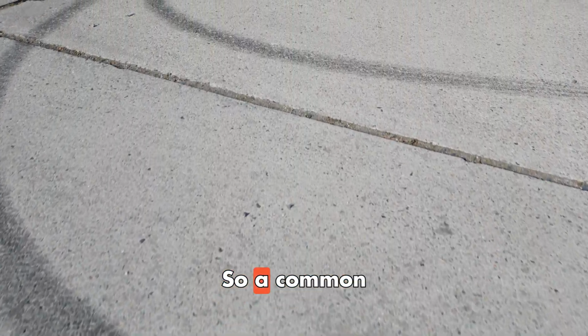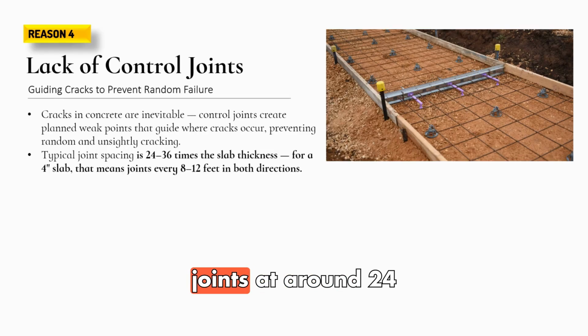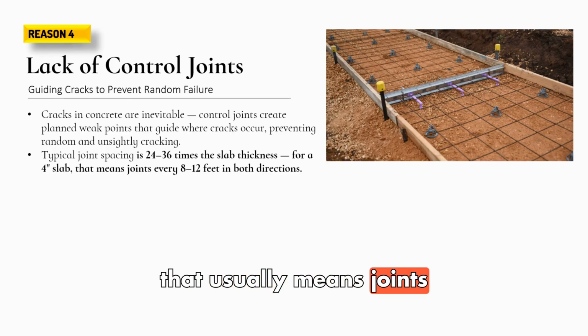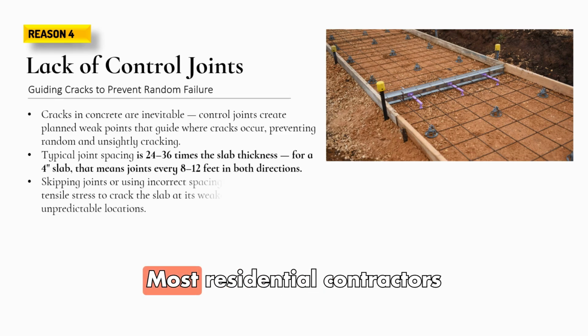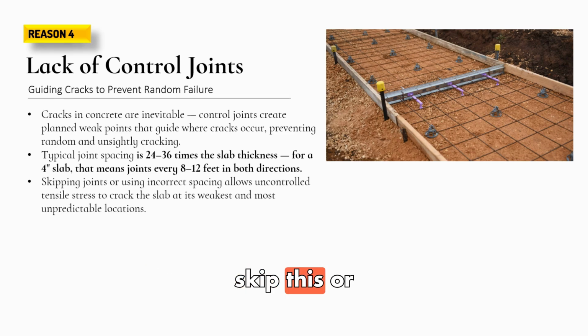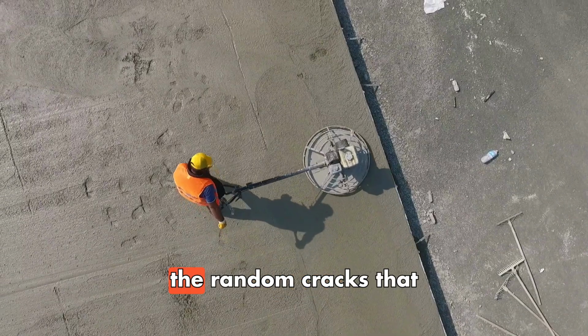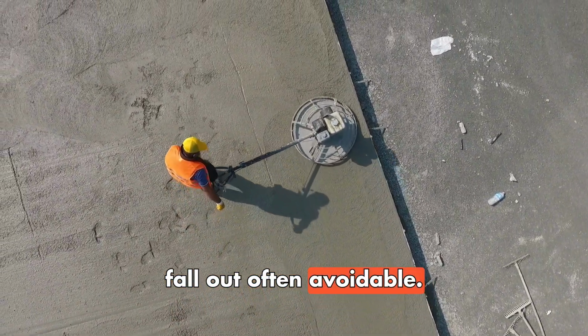So a common rule of thumb is to space control joints at around 24 to 36 times the thickness of the slab. For a 4-inch slab, that usually means joints every 8 to 12 feet. Most residential contractors skip this or get the spacing wrong, and the random cracks that follow are often avoidable.